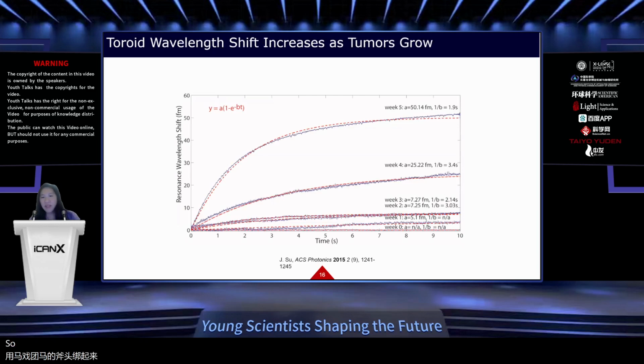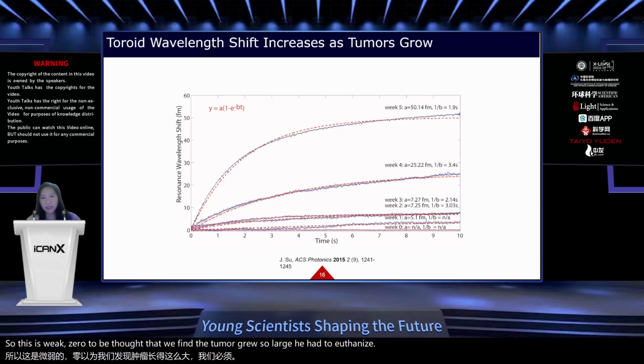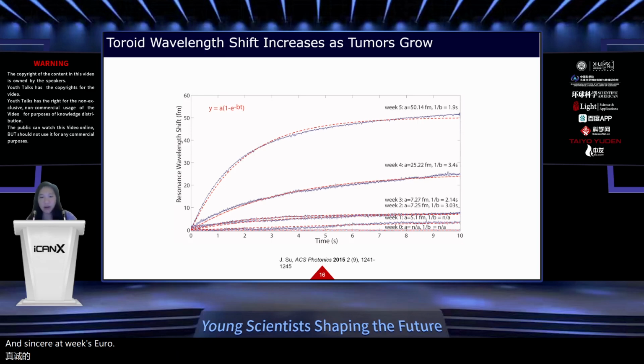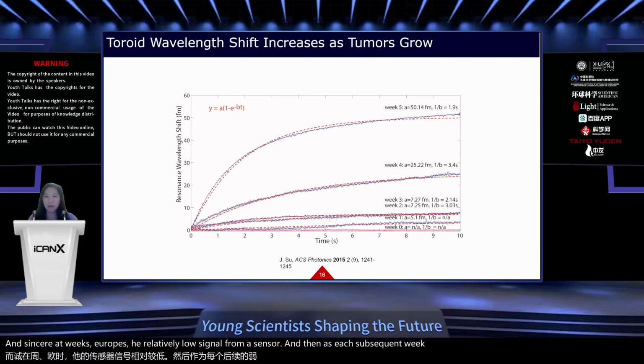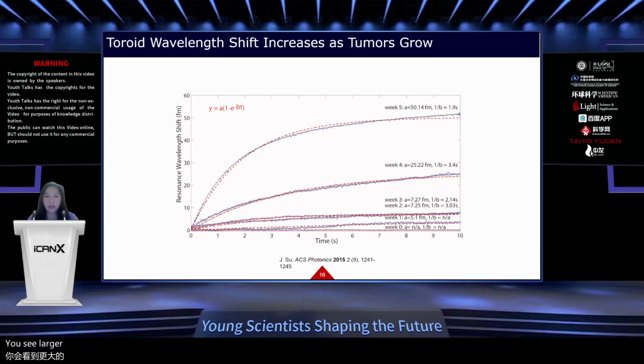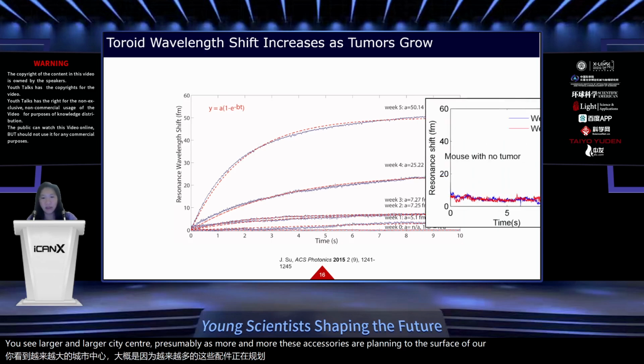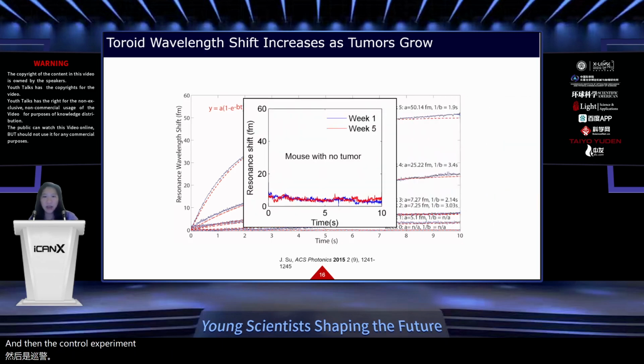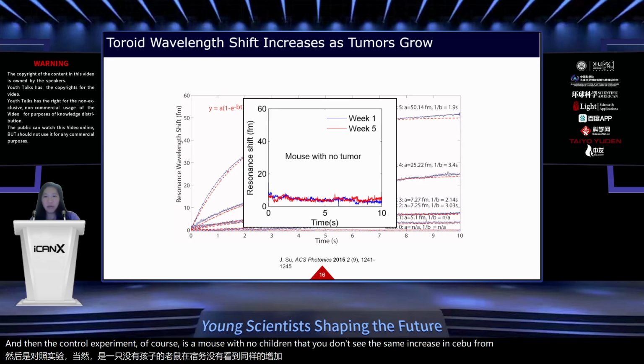So this is week 0 to week 5. At week 5, the tumor grew so large we had to euthanize the mouse. And as you can see, at week 0, you see relatively low signal from our sensor, and then as each subsequent week progresses, you see larger and larger signal on our sensor, presumably as more and more of these exosomes are binding to the surface of our sensor. And then the control experiment, of course, is a mouse with no tumor, where you don't see the same increase in signal from week 1 to week 5.